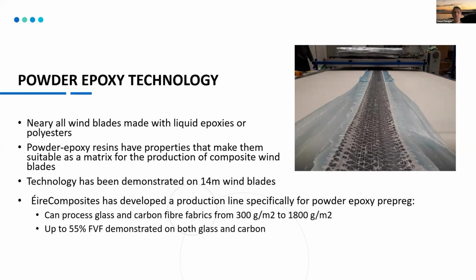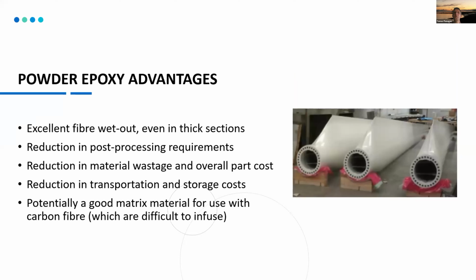And we've used this to make production blades up to 14 meters. And we developed a line for taking the dry fibers and adding on the powder epoxy for different fabrics. And we achieved fiber volume fractions of about 55%. Some of the advantages: you get really good wet out, especially for thick sections. You have reduction in post-processing requirements, reduction in material wastage.